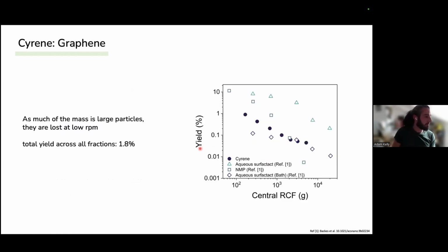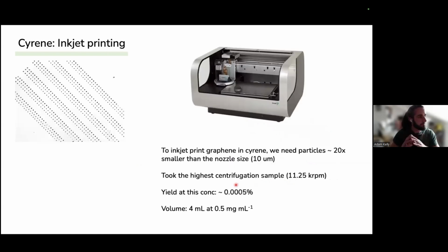If we look at the yield, which is the total mass of the fractions that we got out at every centrifugation, we find that because most of the mass that you create during sonication is large particles, during the first centrifugation step, you pretty much lose all of it at low RPM. So if we sum up the masses across all of these centrifugations, we get about 1.8% total. So this is much lower than working in NMP or water, but it is slightly higher than working in bath sonication, which is also quite an inefficient process.